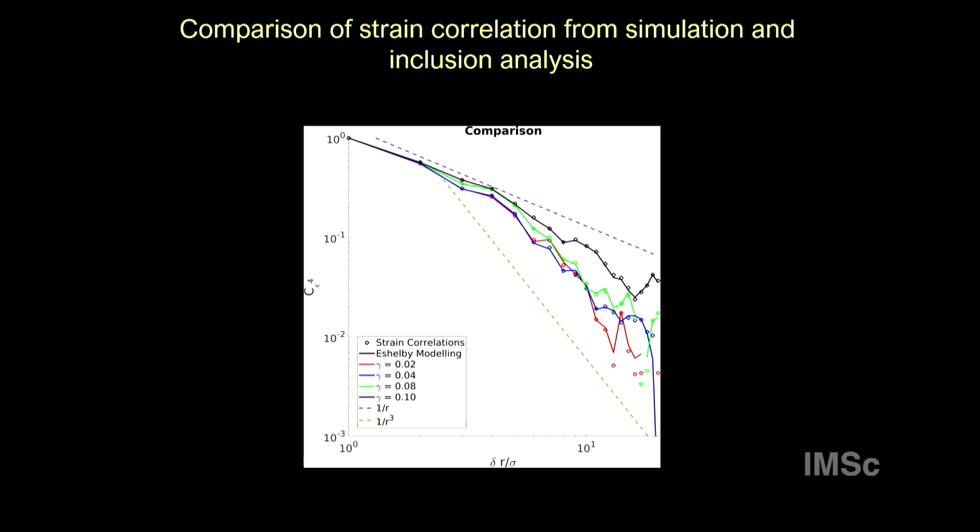So if you start with a somewhat poorly annealed sample, and there are a lot of zones which are susceptible to this, and you compute the strain correlation, you will expect that the power law will remain 1, right? So far it has been very robust. We have seen it in experiments, and we have also seen it in simulations. It looks like these defect zones, and the distribution of these Eshelby zones, are very important, yes, exactly, to have this 1 over r.